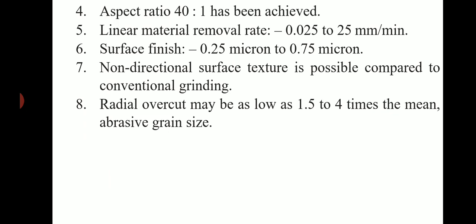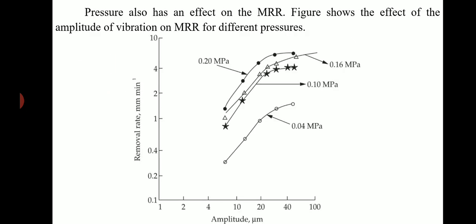Surface finish is 0.25 micron to 0.75 micron. Non-directional surface texture is possible compared to conventional grinding. Radial overcut may be as low as 1.5 to 4 times the mean abrasive grain size. Pressure also has an effect on the material removal rate. The figure shows the effect of amplitude of vibration on material removal rate for different pressures.